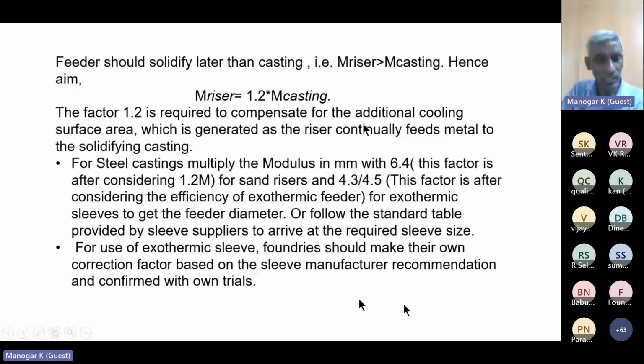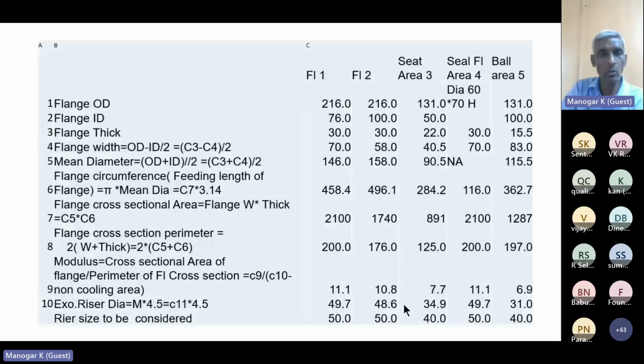The foundry should make their own standard correction factor based on the sleeve manufacturer's recommendations, and do a cube test and confirm the sleeve efficiency with a factor of safety. So we go as per the drawing: F1, F2, F3, F4, all the sections. We enter the dimensions and find the mean diameter, casting thickness, the circumference, cross section area, and now the modulus and the non-cooling area.